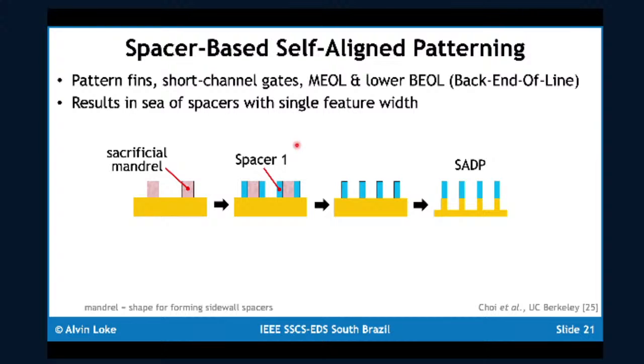Self-spacer based patterning is the key trick that's been used, sometimes called sidewall image transfer. The goal is to pattern a sea of spacers with a single feature width. We use this technique to pattern fins, short channel gates, middle end of line, as well as lower back end of line patterns.